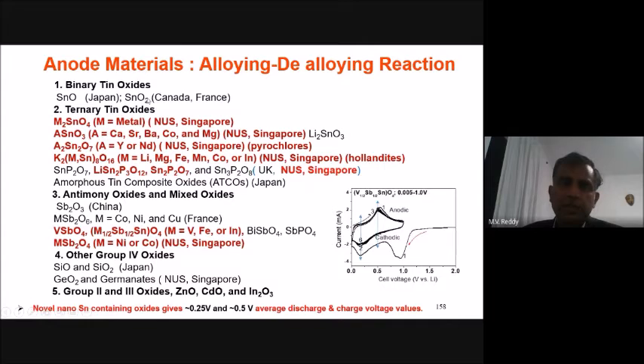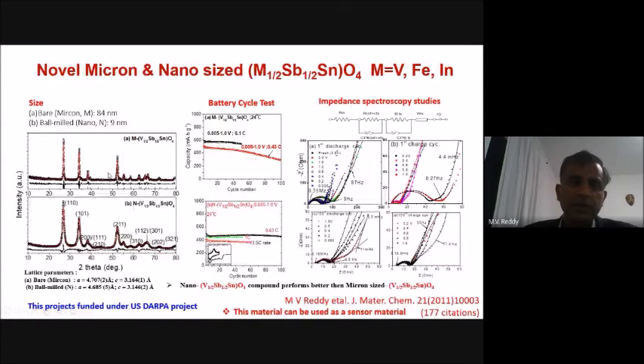In the case of tin-based alloy-forming elements, a lot of oxides were reported earlier from our group. The overall summary is that the voltage is somewhere from 0.25 to nearly 0.5 volts in the case of tin-containing alloy-forming elements. Still, the challenge is that the irreversible capacity in the first cycle needs to be reduced. That is a little challenging in this type of oxide. In one example, going from nano size to submicron size materials, the nano seems to be good, with reasonably good cycling stability up to 100 cycles, whereas with submicron size you may see small capacity fading after a few cycles.